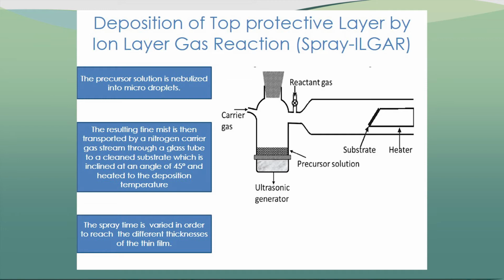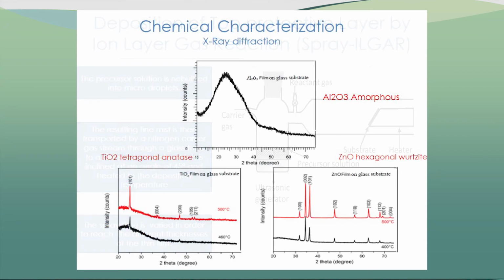If you are interested, she did different thicknesses and worked with different temperatures to see the effects on the structure and the surface of the thin films. These are the X-ray diffraction, XRD, spectra of the three materials. You can see that aluminum oxide was amorphous, of course, at this temperature. We have the titanium dioxide, which is anatase, and you have a hexagonal wurtzite structure for the ZnO.